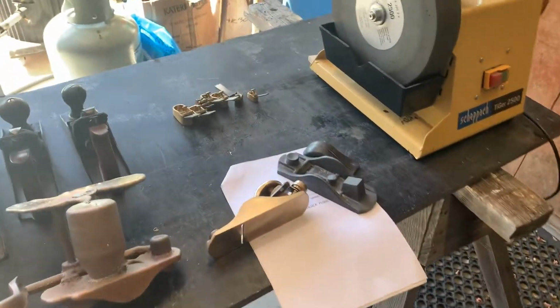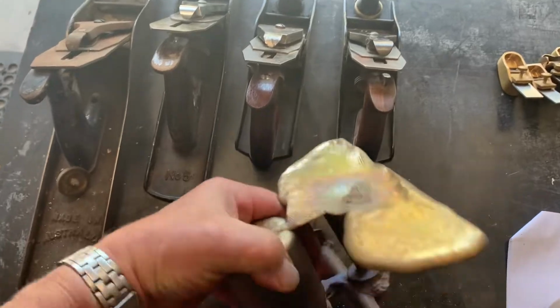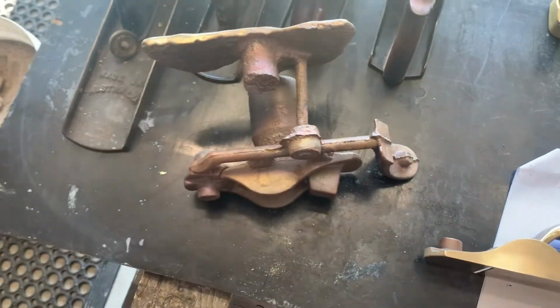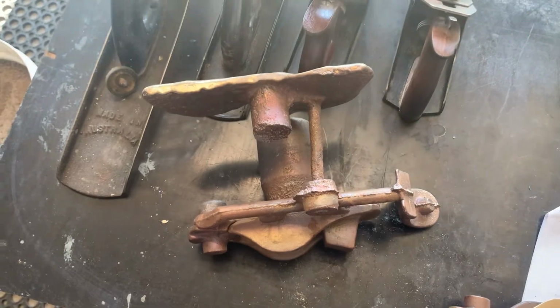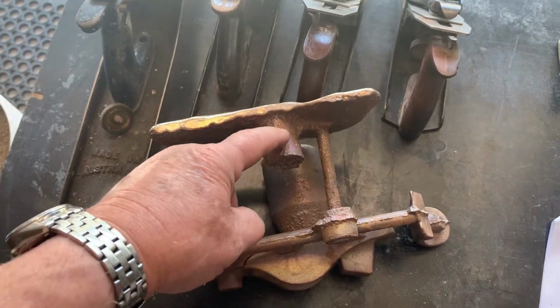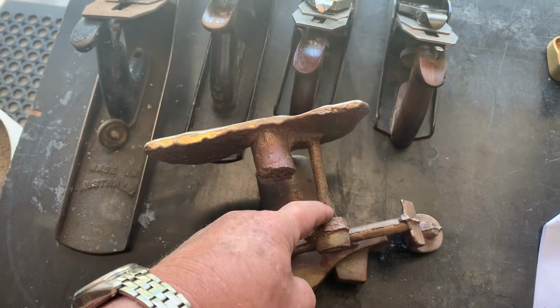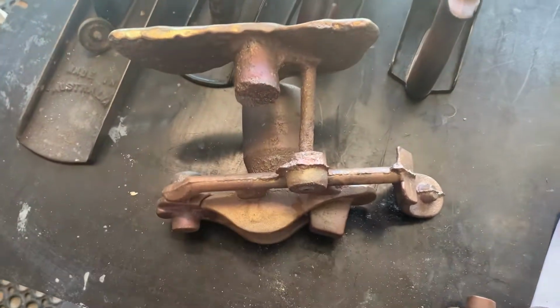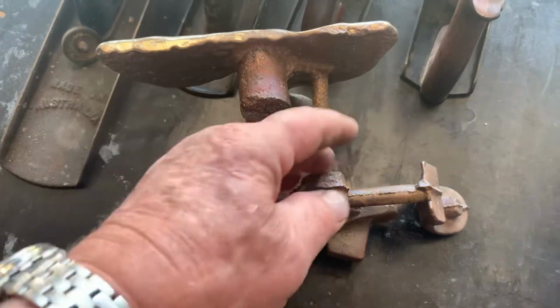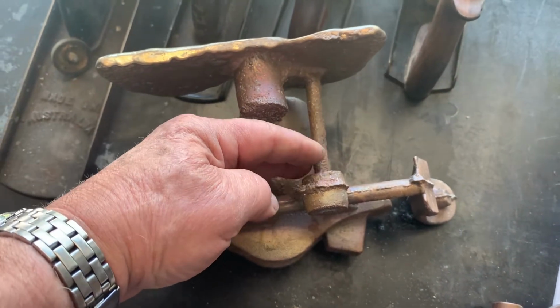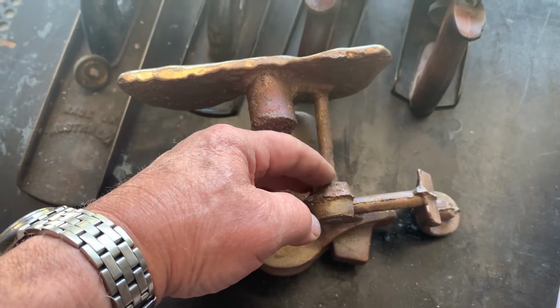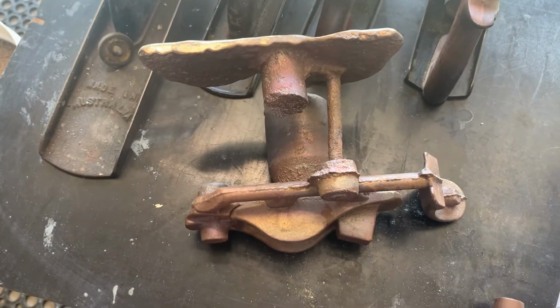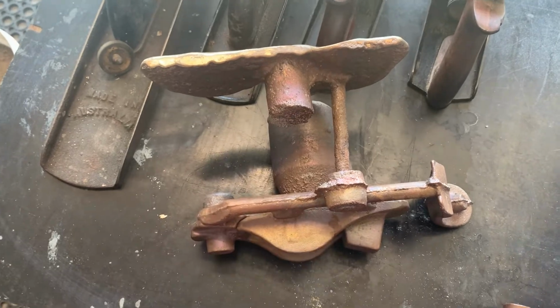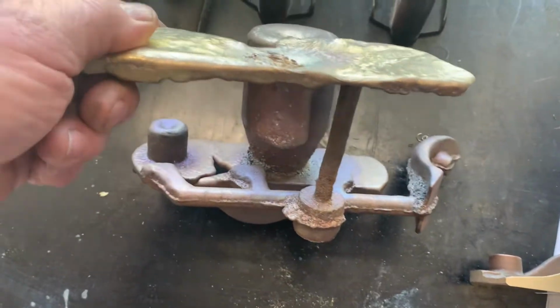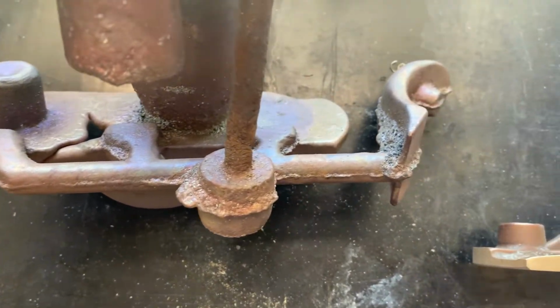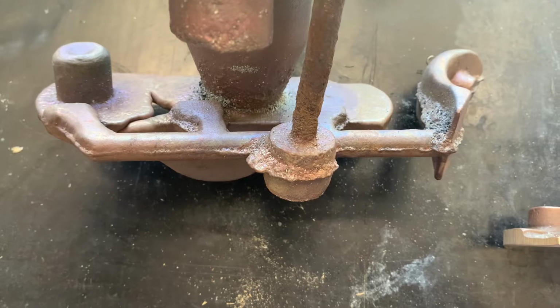Once we've poured it, this is what we get, one that's come straight out of the pour. Here we see the pouring base, we pour in up around here. This is what we call the sprue, and this sprue is tapered. The idea of the taper is that we have a positive pressure coming down, and it stops cavitation, which stops it absorbing oxygen, which causes what we call porosity in your actual melt. It pours into there, and then it goes, as you can see, into little runners into what we want to cast.